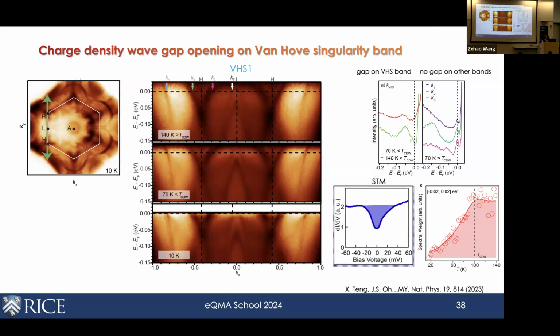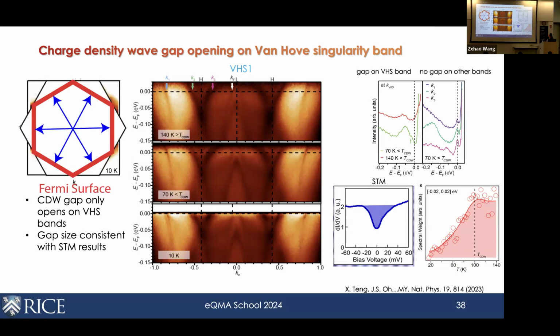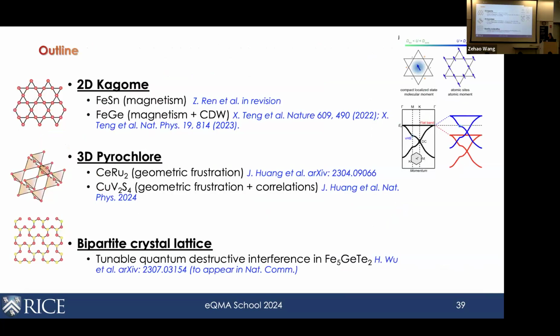And this is actually consistent with what is observed in the STM measurement. This is the dip in the density of states by the STM at the Fermi level, right? So here we can see a spectroscopic evidence for the opening of a gap in the CDW state. Okay, so in that way, this is compatible with the expected 2x2 folding of the Fermi surface.